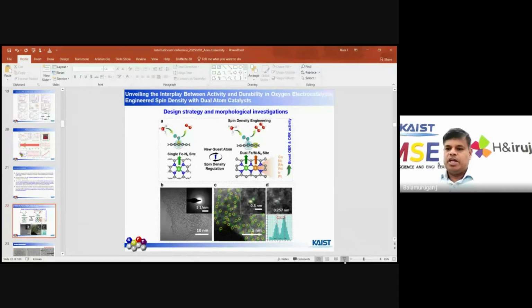We also developed a different type of dual atom catalyst. Previously, I discussed the single atom catalyst like molybdenum. So when we go for dual atom catalyst, I chose the iron fixed one. But when I choose the iron one, I choose 2 first row transition metals, 2 second row transition metals, and 2 third row transition metals. Because I told you the second row and the third row transition metals are more active in acidic media. But the first row transition metals only perform with high performance in basic media like KOH media or sodium hydroxide.